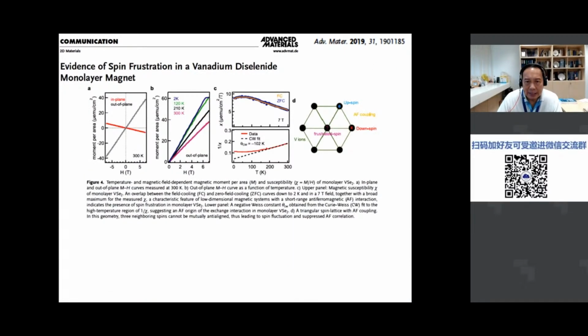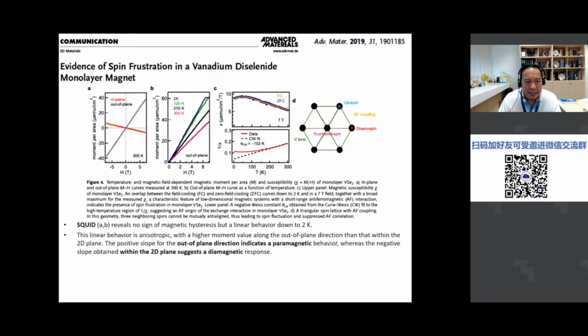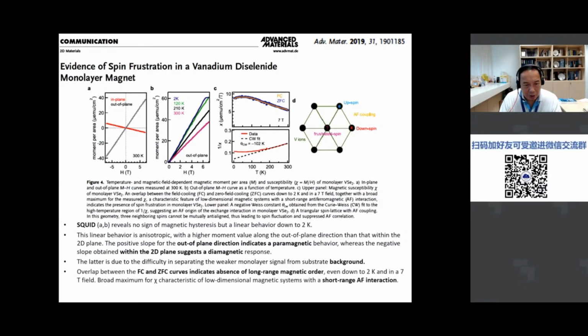And in fact, we did other magnetic measurements. SQUID also shows no sign of magnetism down to 2 Kelvin. And the response is anisotropic, and you get higher moment in the out-of-plane direction than within the 2D plane. So we inferred it is paramagnetic out of plane, and negative slope means it's diamagnetic in the 2D plane. And the latter could be due to the substrate background. And you see overlap in the zero field and field cooling curves, which indicates an absence of long-range magnetic order. And a broad maximum in the susceptibility indicates some short-range anti-ferromagnetic interaction.